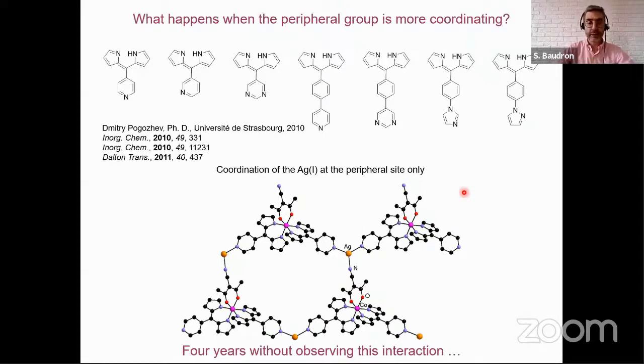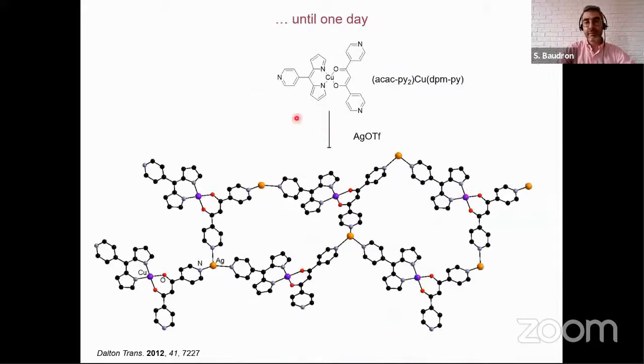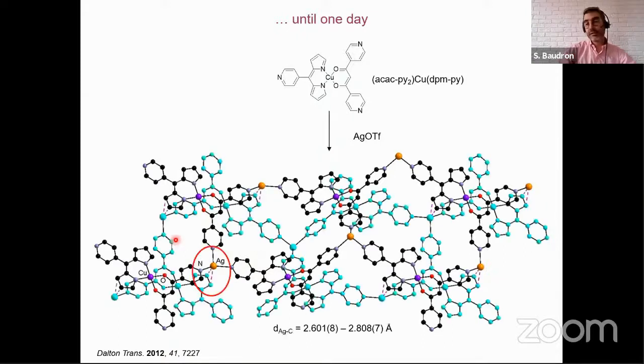It turns out that actually we were probably wrong, because one day, while we were studying this heteroleptic copper complex bearing here an acetylacetonato ligand with 2 pyridyl units and a dipyrrin with a pyridyl unit at the periphery, the ligand that you've seen before, Antoine Béziot observed this two-dimensional coordination polymer where the silver is coordinated to the 3 peripheral pyridyl groups, forming two-dimensional sheets. But those sheets do stack in the crystalline state by a silver-pi interaction, with a distance here between 2.6 and 2.8 angstroms.